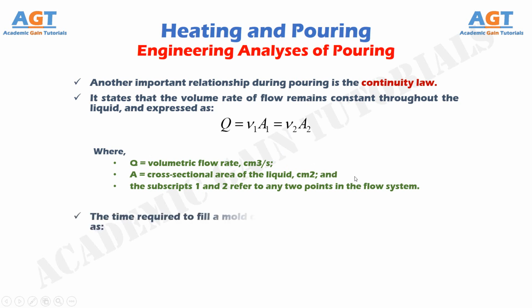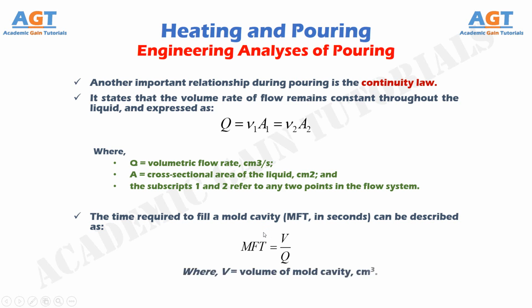The time required to fill a mold cavity, MFT, in seconds, can be described as MFT equals V divided by Q, where V equals volume of mold cavity, expressed in cubic centimeters.